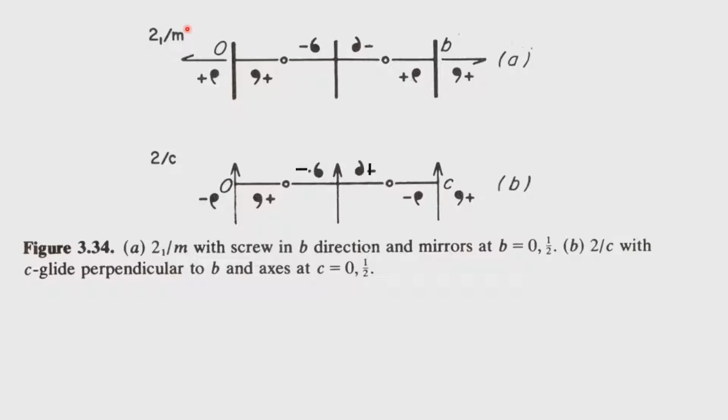Since the point group is 2 by m, it will represent a center of symmetry. So, the presence of the center of symmetry invokes the requirement that we should have a center of symmetry in the system. The fact that we have a center of symmetry in the system, we have to associate that with 0 0 0. So, once we do that operation, what we have to remember is whenever there is a non-translation involved component, that is the one which moves by 1/4, and the translation component will stay along with the center of symmetry.